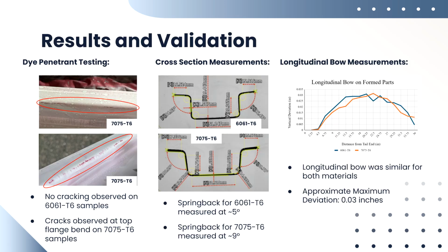For dye penetrant testing, no cracks were found in the 6061 T6 samples. However, the 7075 T6 samples showed small hairline cracks at the top flange bend. Cross-section measurements showed springback of about 5 degrees for 6061 T6 and 9 degrees for 7075 T6. Longitudinal bow was similar across both materials, with a maximum deviation around 0.03 inches.